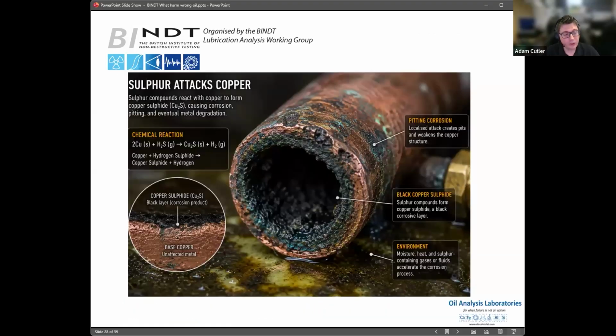Well, no, it can also be other additives as well. So a common one is EP, extreme pressure oil additive, which is used in many, many gear oils and gives that sulfury, unpleasant smell you can smell in gear oils. Now, these are really good for wear protection, but one of the disadvantages is that EP can attack copper components. And this can eventually, over time, lead to copper sulfide formation and eventual, over a very long period of time, tarnishing and dissolving of components in a gearbox over time.